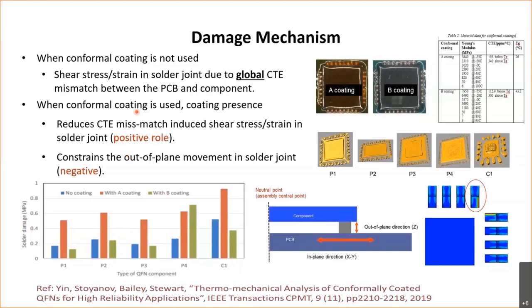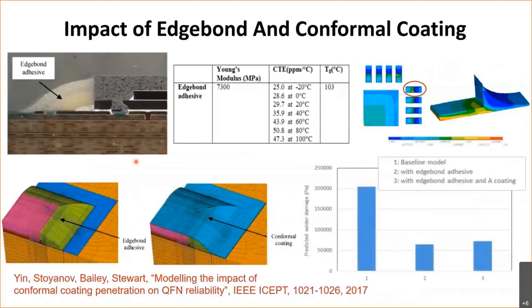In essence, when using a conformal coating, it reduces the CTE mismatch induced shear stresses and strain in the solder joint. That's a positive role, but it constrains the out-of-plane movement of the solder joint. So there's two influences here happening when those solder joints are surrounded by a conformal coating. We also looked here at edge bond adhesive.